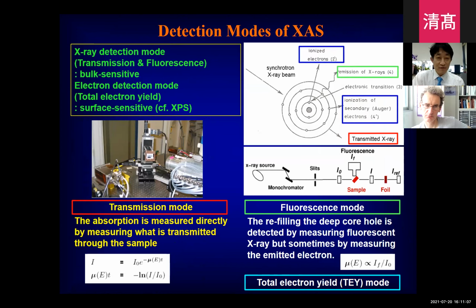I know all of you are very familiar with this detection mode of XAS. I want to emphasize that we can use the X-ray detection mode and the electron detection mode. Transmission and fluorescence modes detect the X-ray, but in total electron yield mode, we can detect the electron. Due to the strong interaction between the electron and matter, in electron detection mode we can get the information of the surface, but in the case of the X-ray, it has a much weaker interaction, so we can effectively probe the bulk species. So by combining them, we can get separate information about the chemical bonding nature in the bulk and surface.